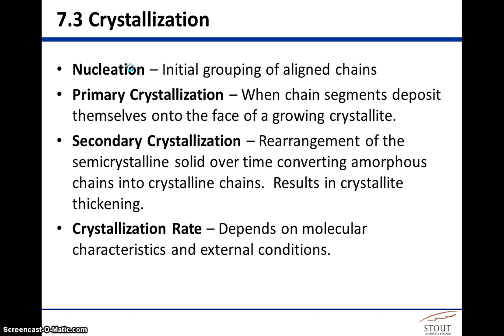Secondary crystallization is rearrangement of the semicrystalline solid over time, converting amorphous chains into crystalline chains. That results in kind of a bulking up of, or I guess, crystallite thickening. And so that would be if you were to hold the temperature at that crystallization temperature, sort of annealing is the term that's used, annealing the material, allowing those crystals to grow and attain their maximum size, their highest percent crystallinity possible.